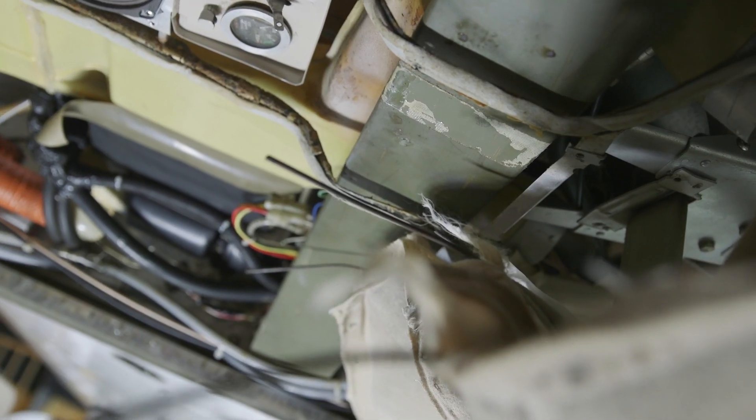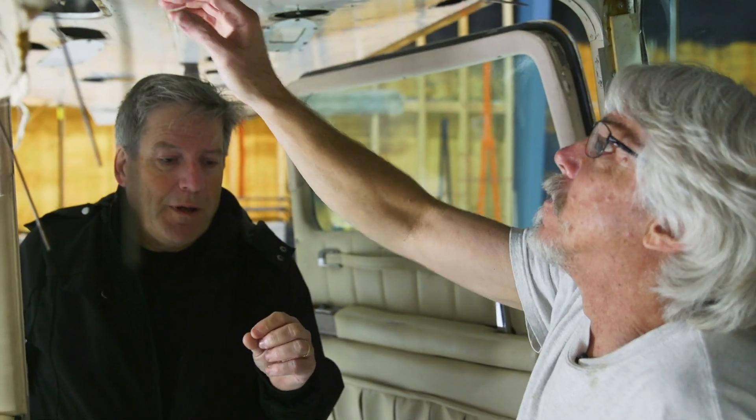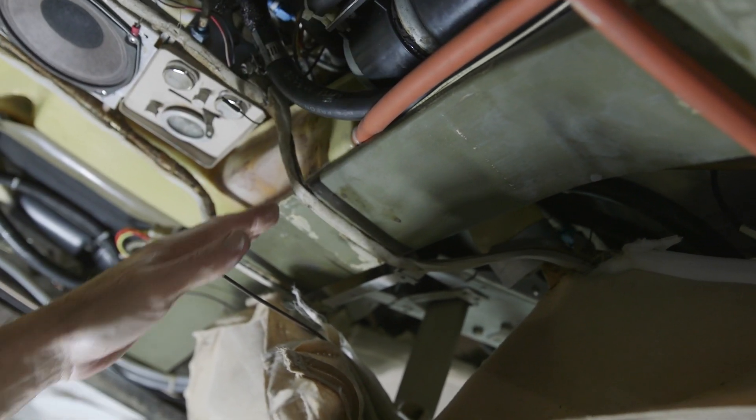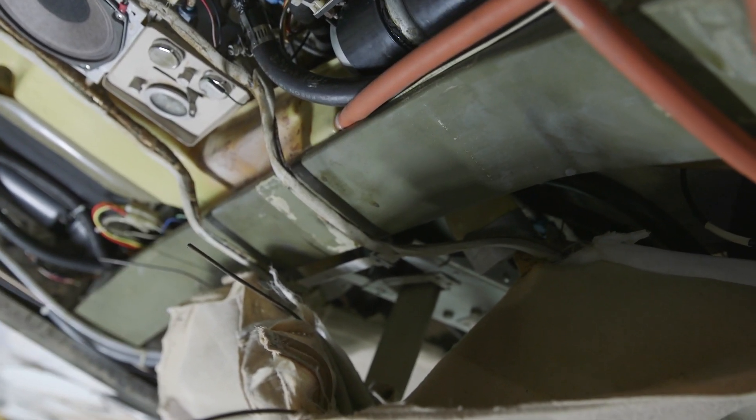This plane's been mostly dry, clean climate. We did have the air conditioner, but the primers protected it. And this doesn't have the glued-on foam. That's been the real issue for some people, because the foam covers that area and attracts moisture like a sponge — it's all stuck to it, so you've got to scrape all that foam off. You have moisture that's retained, whatever environment they're operating in, salty condensation, salt air, and the glue combination may have also had an impact. It's just a setup for corrosion — and that's the problem that has been brought to light with this new service bulletin.